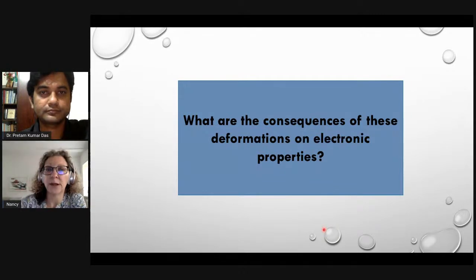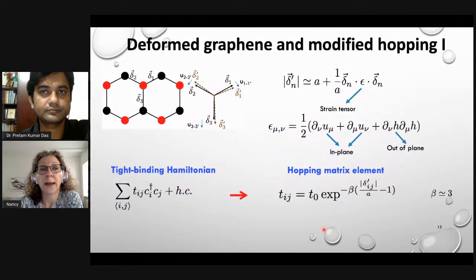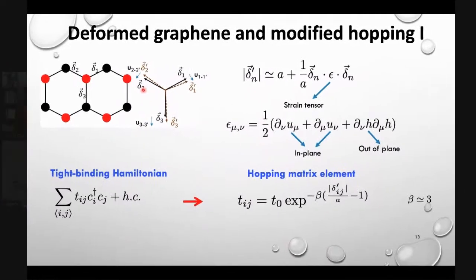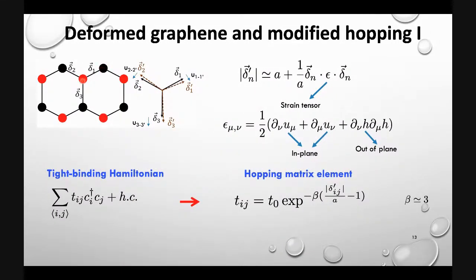So what we did was to say, okay, well, let's imagine what happens when you deform graphene. When you deform graphene, you are basically changing both the length and the angle of these nearest neighbor vectors, because you are changing the atomic positions of the carbon atoms. So for a given atom, the other three that surround it as nearest neighbors will be located at different positions. For instance, this atom here will be displaced by a vector u1, 1 prime. This one here will be displaced, and this one here will also be displaced.